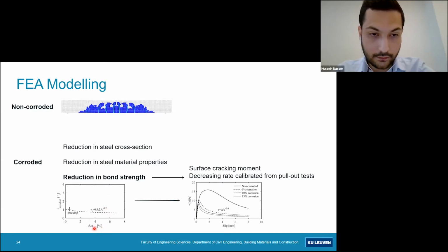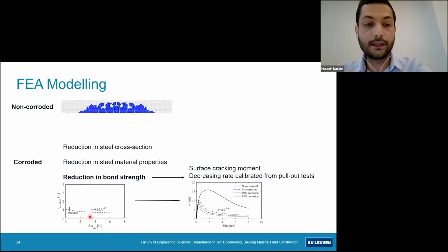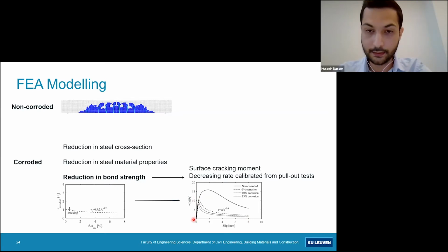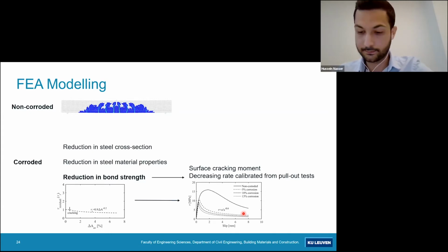After obtaining this curve, I can find the residual bond strength based on the average cross-section loss. And I can build the deterioration curves shown here based on the non-corroded curve. So if I would calculate, for example, the residual cross-section loss from the decreasing curve, I would correspond it to the point on the non-corroded curve, and I will build the deterioration curve based on, first of all, a linear increasing curve, and then a decreasing curve. This has been done for every corrosion level, and these were implemented in the model.